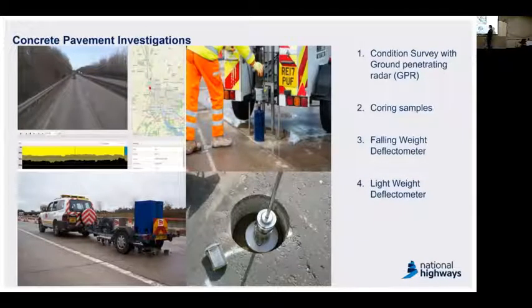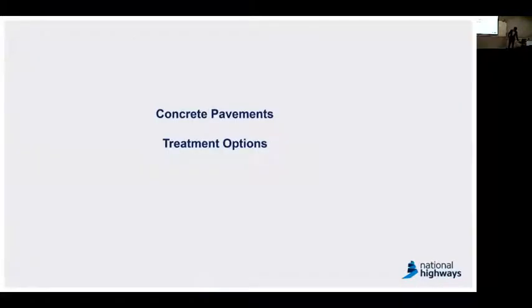The one on the bottom right corner is something called the lightweight deflectometer. Once you've taken a core out, you can use the core hole to use this lightweight deflectometer just to understand the condition of the subgrade. It gives you the surface subgrade modulus, and then you will get an indication of the strength of your foundation. So with all sorts of investigation techniques, it's quite important to work out the root cause for individual defects. There is no such one-off treatment that can fit everything. So it's really important to work out the root cause for each of those defects. Then you need to come up with a maintenance strategy.